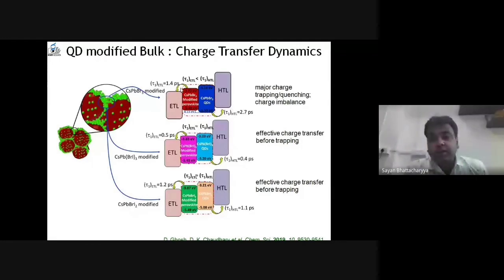So that's how this system, CsPbBr3, does not work very well, because the electron and hole are not being extracted at the same time. But when you have this system, you see on this interface here, it is 0.5 picosecond. On this interface, it is 0.4 picosecond. It is nearly similar. So at the same time, electron hole can be transferred.